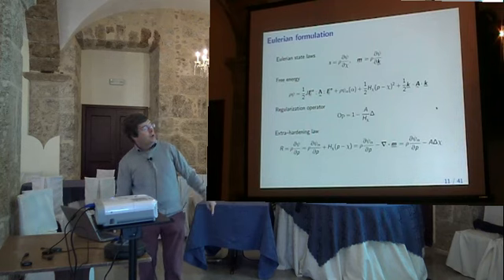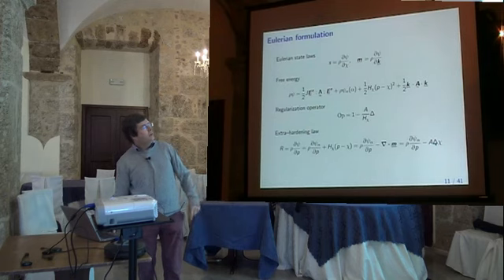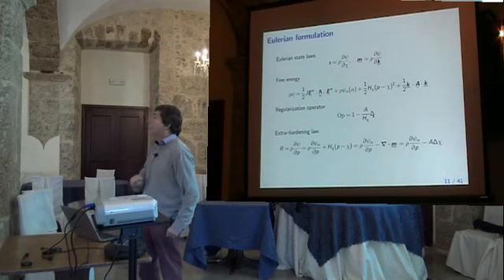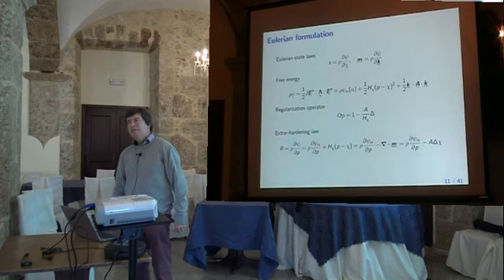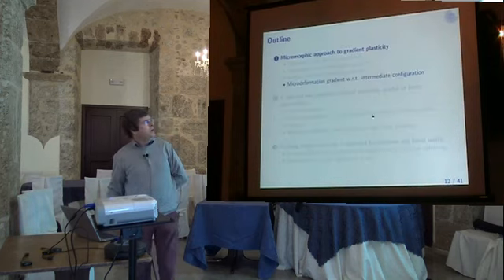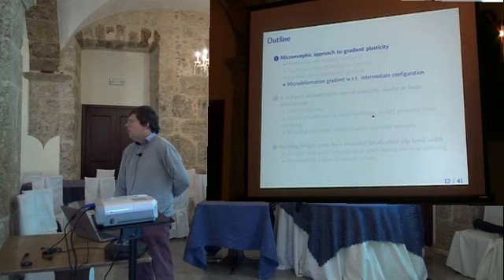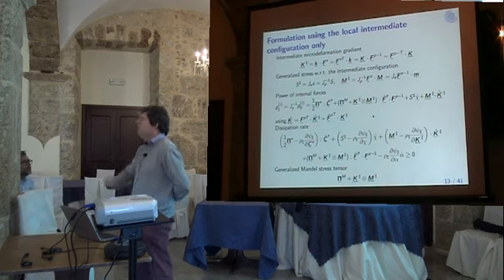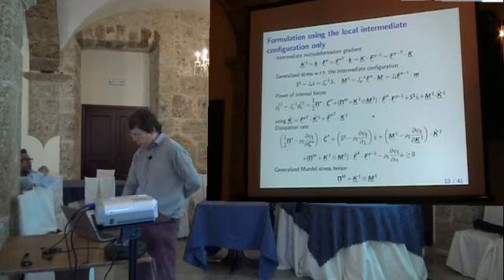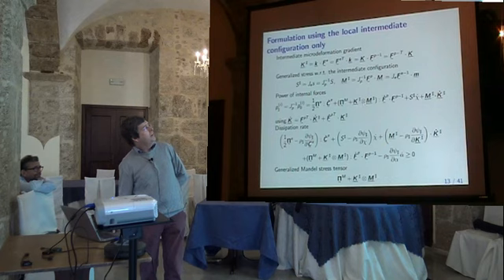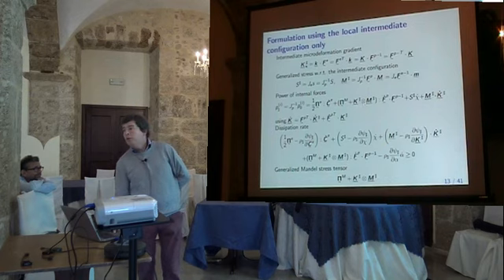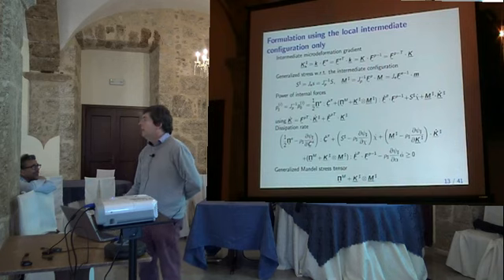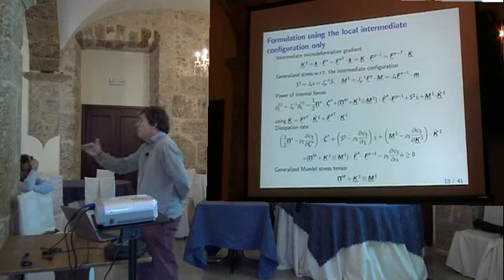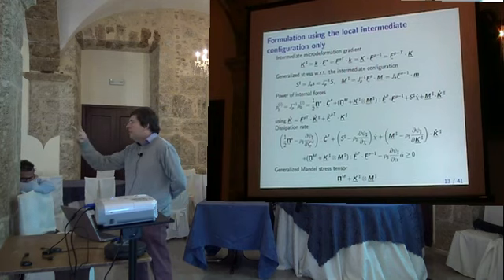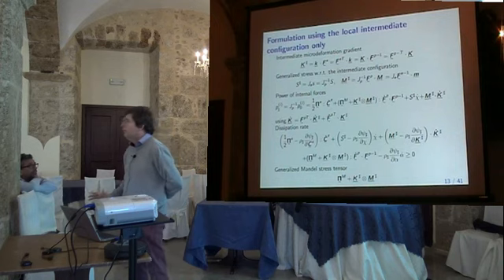And then you end up with, again, a sort of regularization equation here, where you have a Laplace operator, but an Eulerian Laplace. So this is what you get. And in fact, there is something in between, because you could also ask, why Eulerian, why Lagrange? We are working on the intermediate configuration. It's better for plasticity. So we should transport the field K on the intermediate configuration. So this is the K sharp. Okay. So this is the third choice. Of course, there are others, but I say in this case of multiplicative decomposition, you have at least 3 choices for your constitutive law. They are all different, of course.